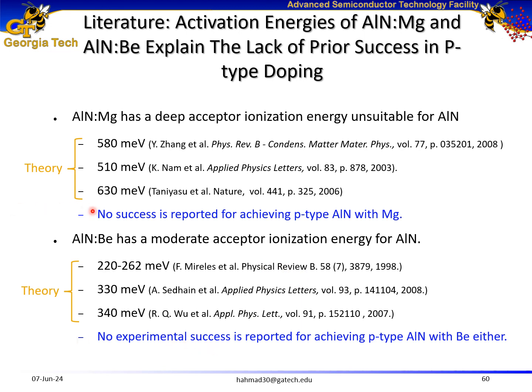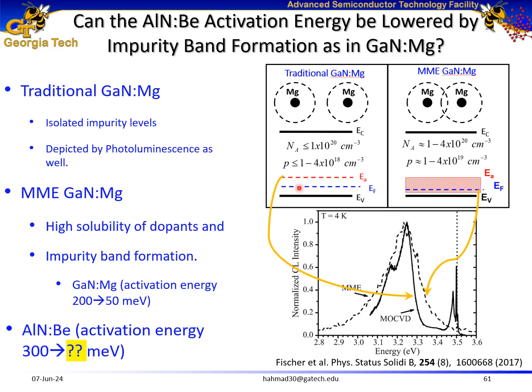Generally, the theory agrees that the activation energy of beryllium is lower as compared to the activation energy of magnesium in aluminum nitride. The activation energy of beryllium in aluminum nitride is found to be approximately 300 milli-electron volts. In traditionally grown magnesium-doped gallium nitride, we find isolated impurity levels, which is also depicted by its two peaks in photoluminescence measurements. Now, on the contrary, in metal modulated epitaxy, we can achieve high solubility, and also we achieve impurity band formation overlapping the valence band of the semiconductor, which is also depicted by a single photoluminescence peak where the band overlaps that of the gallium nitride 3.4 electron volts band gap.